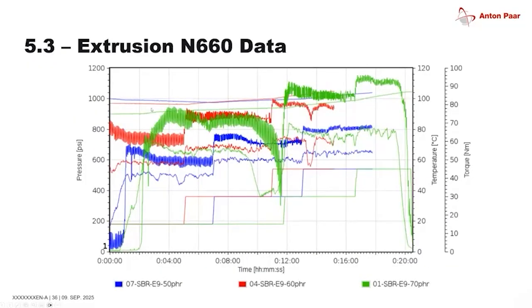So again, we go to the test where we compare just the different load levels of the N660. So this looks a little convoluted, but just bear with me. This is our comparison data. You always see the steps of speed here at the bottom. This is always 30, 15, 30, 45. And you see this for all different. 50 PHR is blue, 60 is red, and 70 is green. 70, again, gave us a hard time. We had a massive drop. What you see here is what happens if something with the roll feed is amiss.